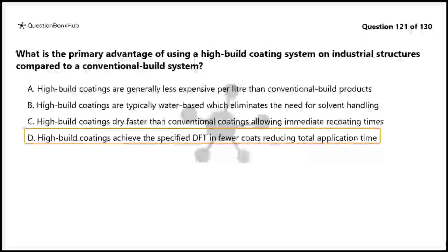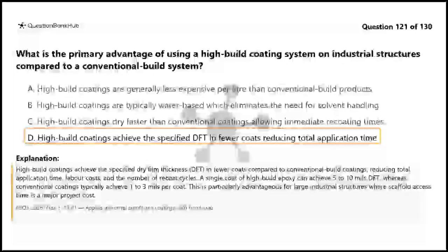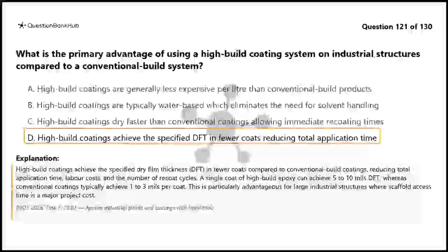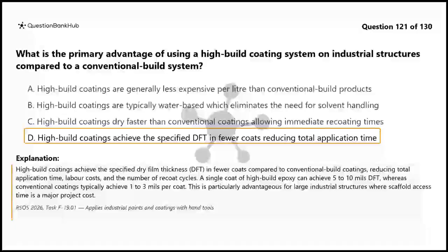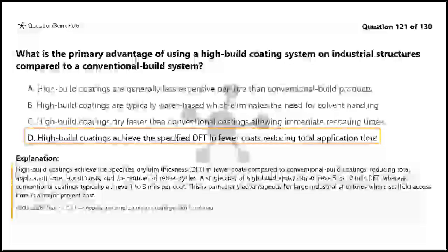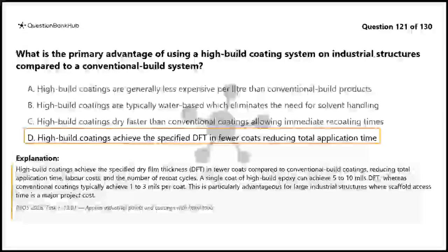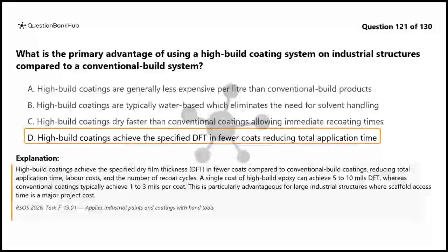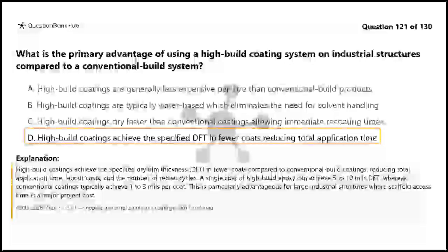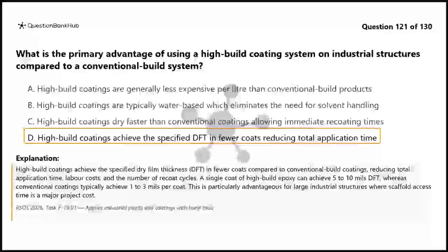The correct answer is D. High-build coatings achieve the specified dry film thickness, DFT, in fewer coats compared to conventional build coatings, reducing total application time, labor costs, and the number of recoat cycles. A single coat of high-build epoxy can achieve 5 to 10 mils DFT, whereas conventional coatings typically achieve 1 to 3 mils per coat. This is particularly advantageous for large industrial structures where scaffold access time is a major project cost.